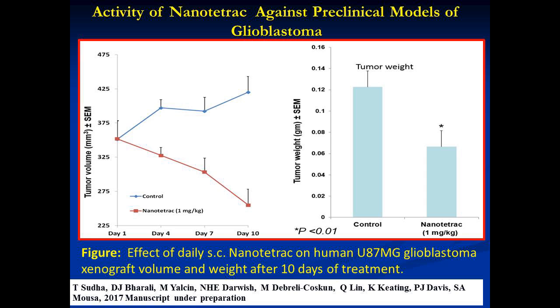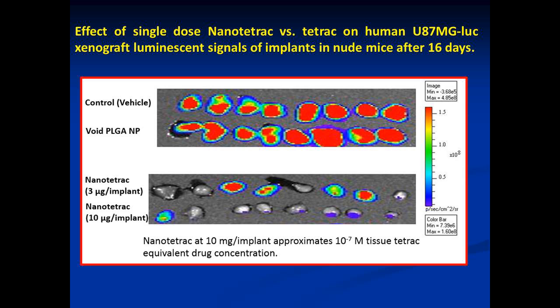The next step was we checked the efficacy of our formulation in a glioblastoma xenograft, and you can see here after 10 days there is a tremendous inhibition of the tumor volume when we use nanotetrac at 1 mg per kg, while the control doesn't have any effect. So the cancer keeps growing in the control, while with nanotetrac there is a tremendous inhibition of tumor growth. Tumor weight shows the same thing. And next slide